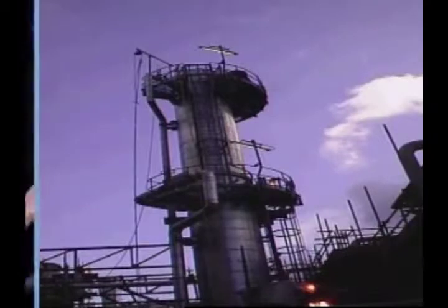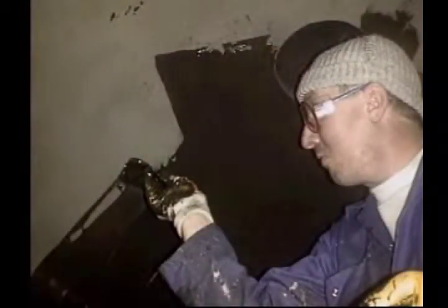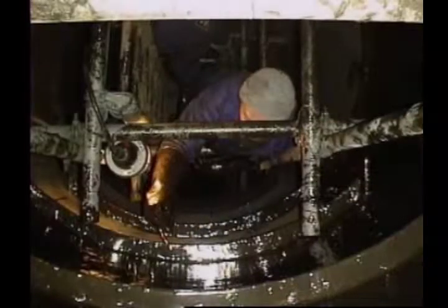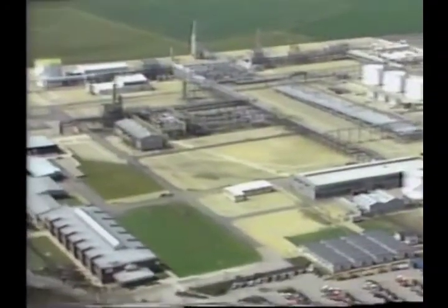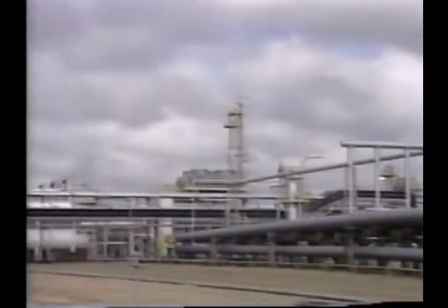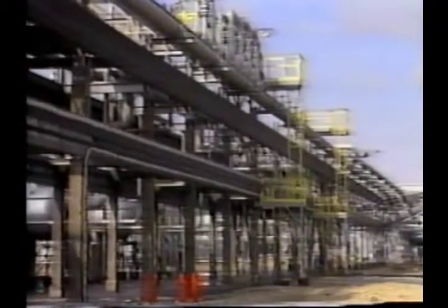Here we can see the effects of the failure of a strip lining where severe pitting corrosion has occurred on the tray support rings and vessel walls. Belzona 1591 can provide a long-term solution to these problems, extending the life of the equipment and reducing outage costs, as has been identified by large gas processing plants where Belzona has proved to outperform traditional weld repair procedures, which only introduce further stress corrosion cracking problems.